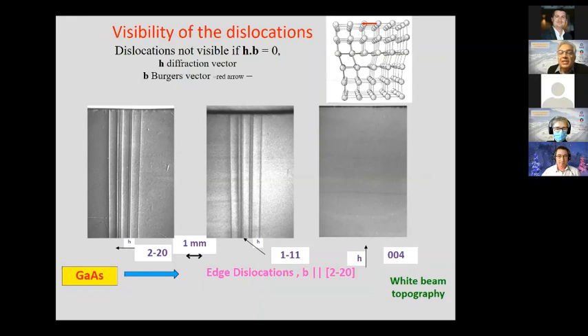That is, when you consider these planes which are there, they are distorted by the presence of the dislocation. But when you consider the horizontal planes which are there, they remain parallel to each other and are not distorted by the dislocation. So when you use these planes to produce the image, you perfectly see the dislocations. And when you use these planes, you don't see the dislocation. That means that you not only see the defects and locate the defects, but you can also characterize the defects through the distortion they induce into the different lattice planes of the crystal.